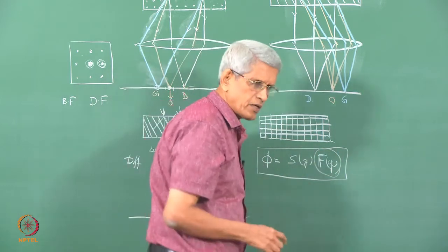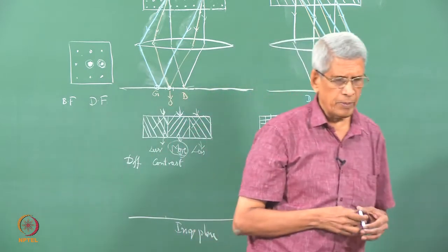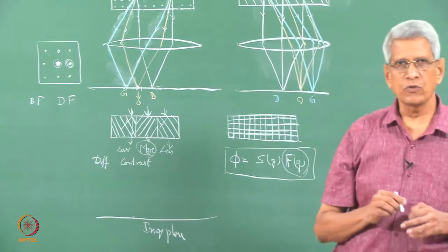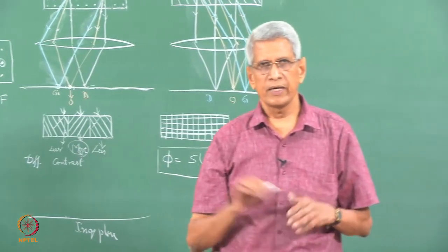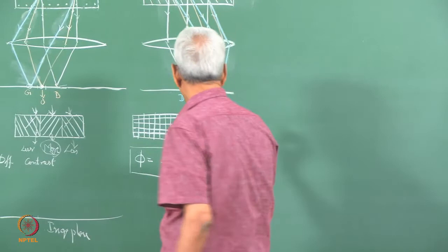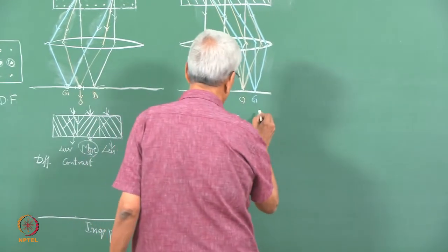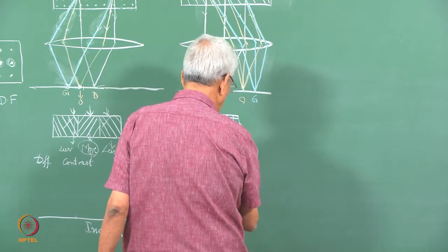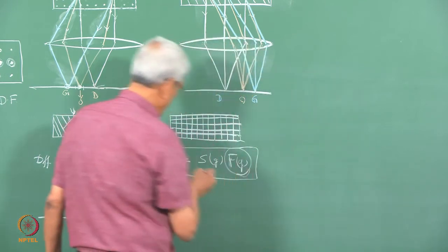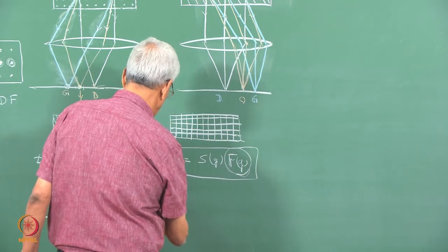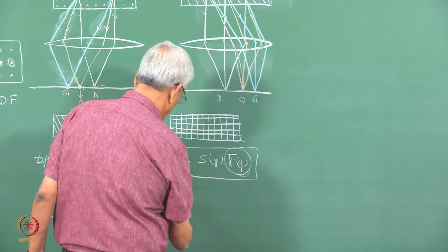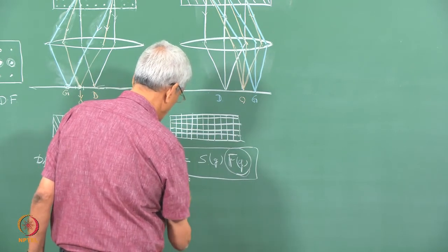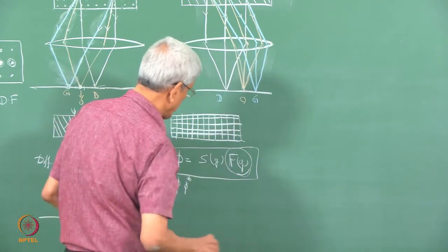And this structure factor formula, depending upon the position of the atoms in that sample, gives rise to systematic absences of reflections, depending upon the type of crystal structure. On that basis we can identify them. But when we have to find out the intensity, it will be nothing but phi phi star, because this is a complex quantity.